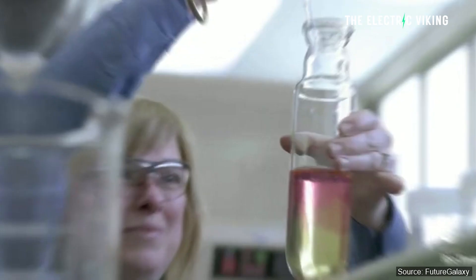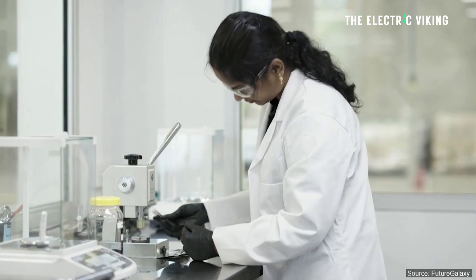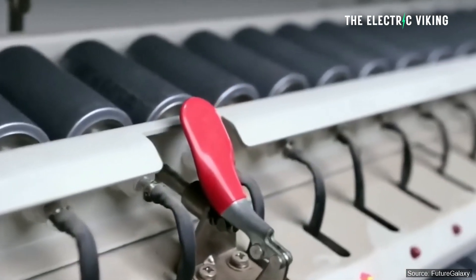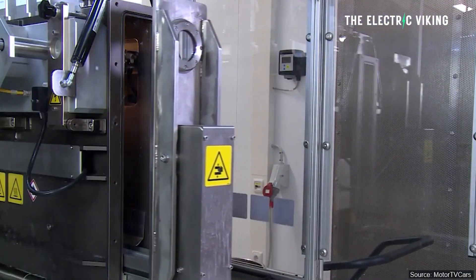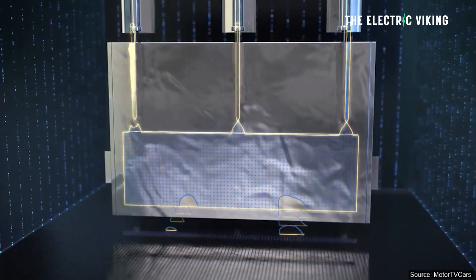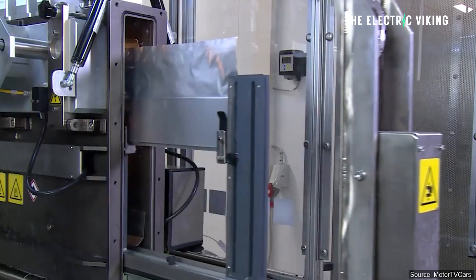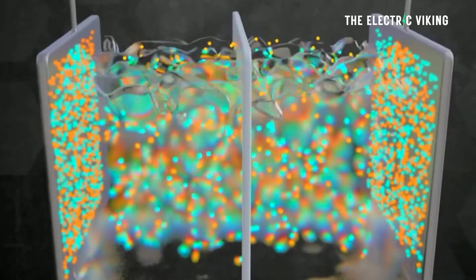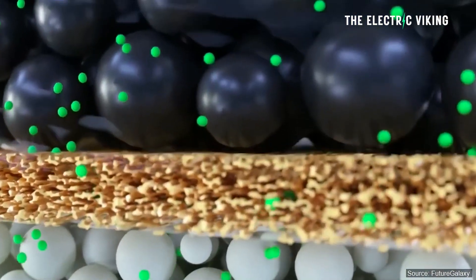Getting back to the actual batteries — in the experiment, aluminium batteries with this electrode material stored a previously unattained capacity of 167 milliampere hours per gram. The organic redox polymer thus surpasses the capacity of graphite, which has mostly been used as an electrode material in lithium batteries to date. While graphite is great for batteries, it holds nowhere near as much energy density as other theoretical cathodes and anodes. Researchers are trying to use silicon, which holds much more energy density, but problems with silicon expanding and contracting during battery use haven't been overcome yet.